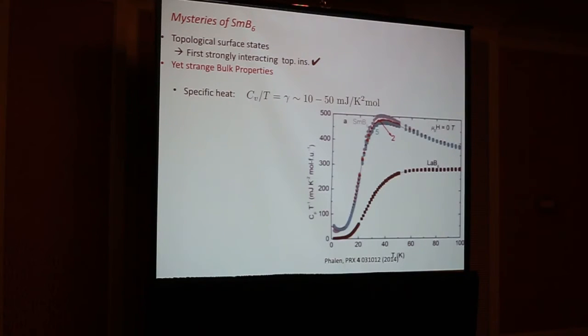of being one of the first strongly interacting topological insulators. But it's got strange bulk properties. The specific heat, measured for a very long time, has a large linear component. There is the linear specific heat capacity that you can measure, and this is the work by Phalen et al. Typically, somewhere between 10 to 50 millijoules per mole Kelvin squared linear specific heat is seen in these samples. Where is this coming from?